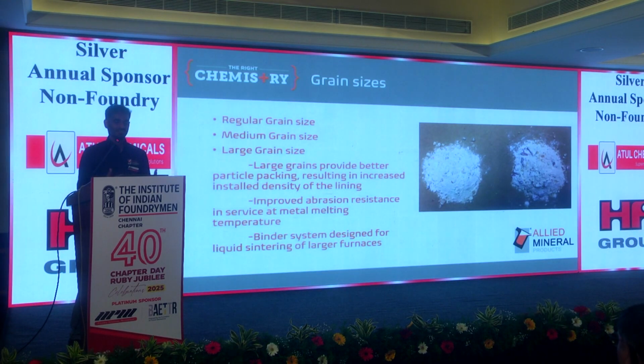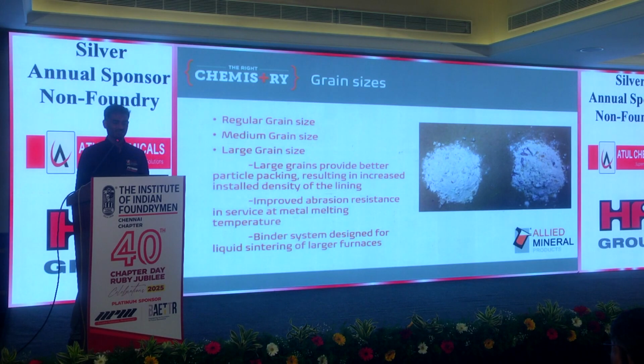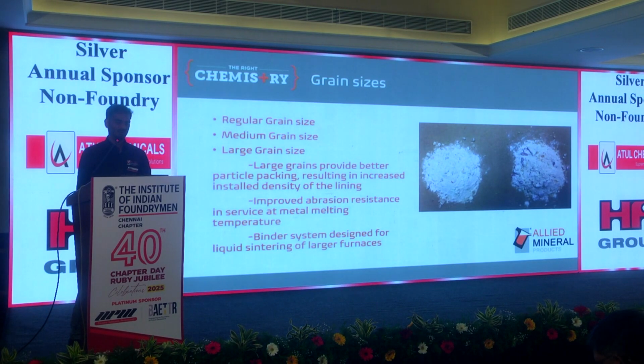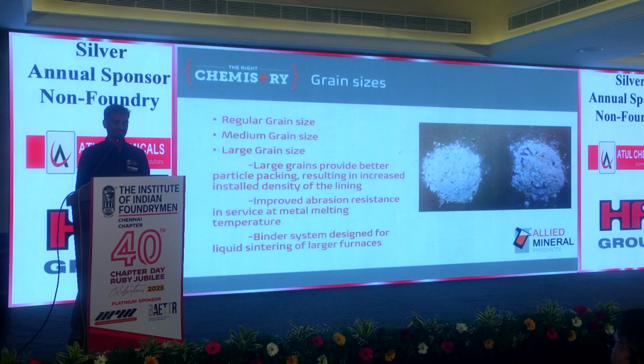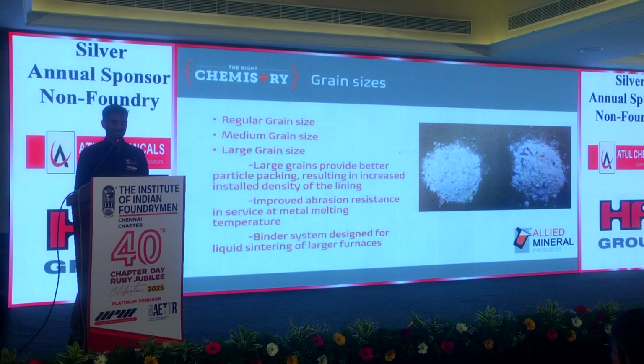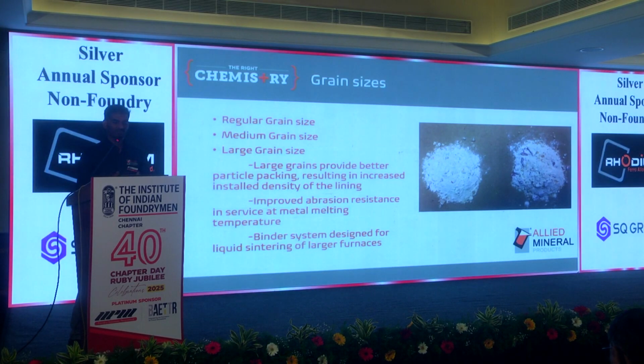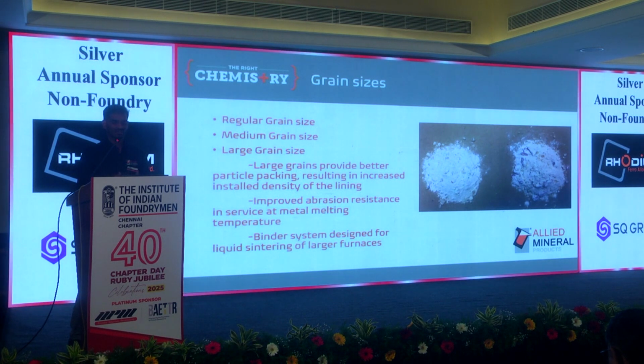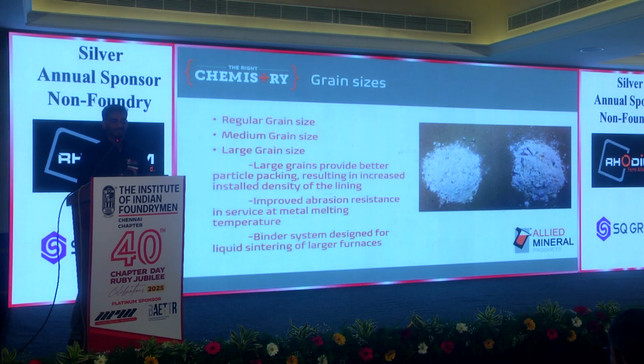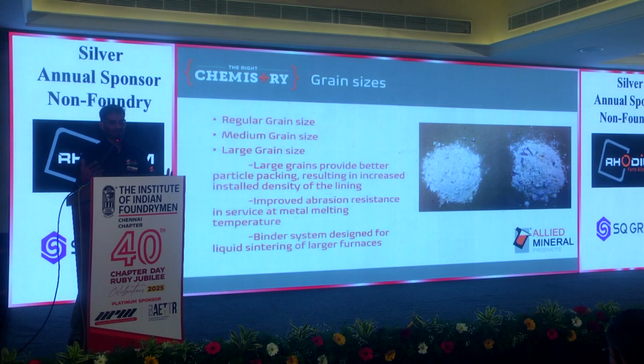what happens is, in large grain silica we had a challenge, because for any lining above 2.5 inches we will be using large grain silica, and for patching, when the patching is only 1 inch or something like that, we can't use large grain silica. So there was confusion at the customer end that they have to stock both the products.